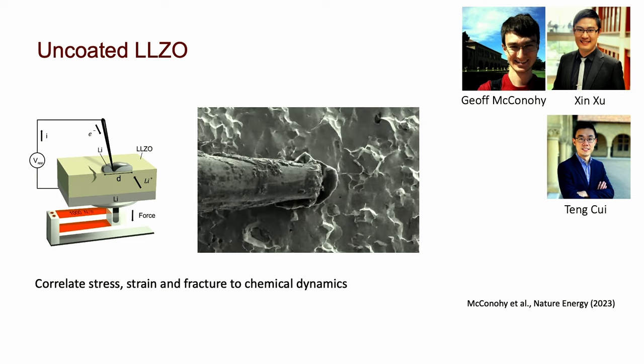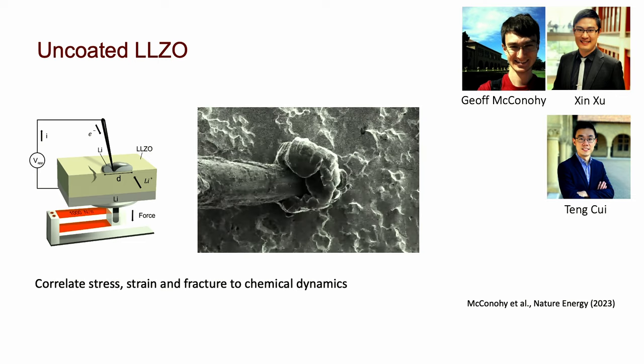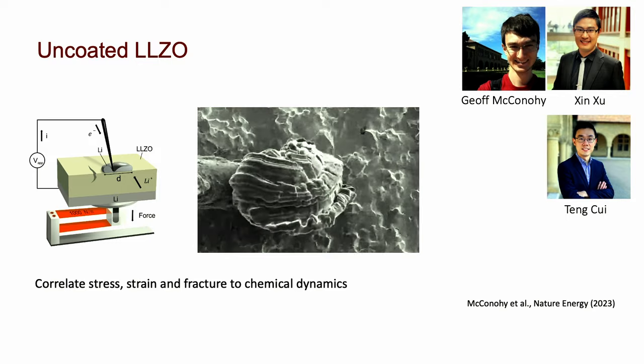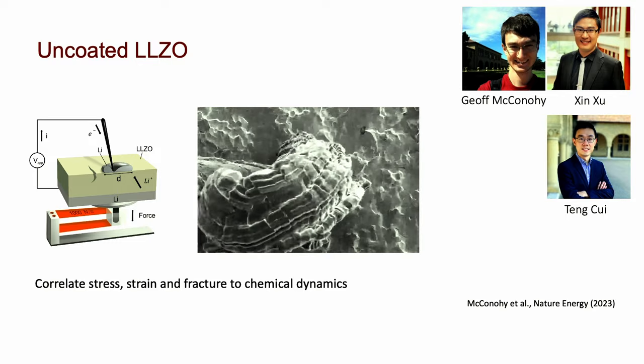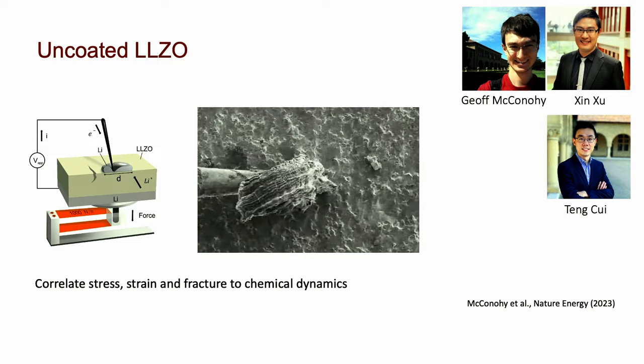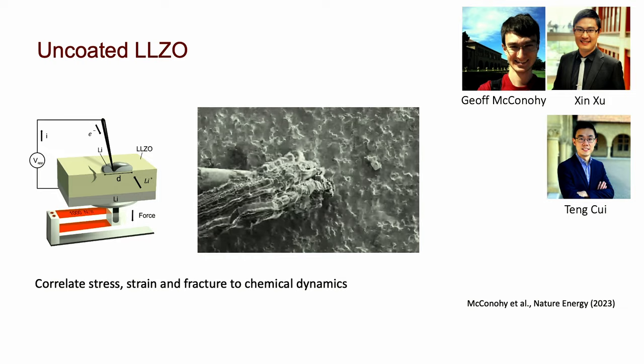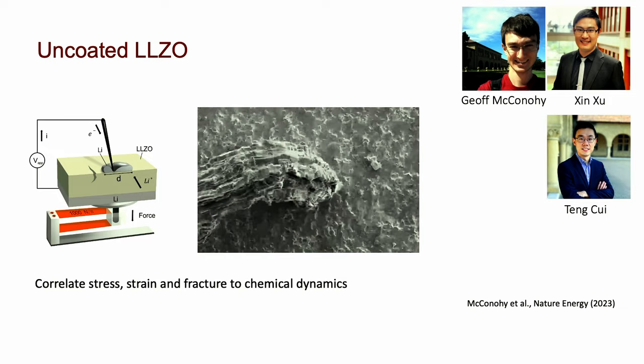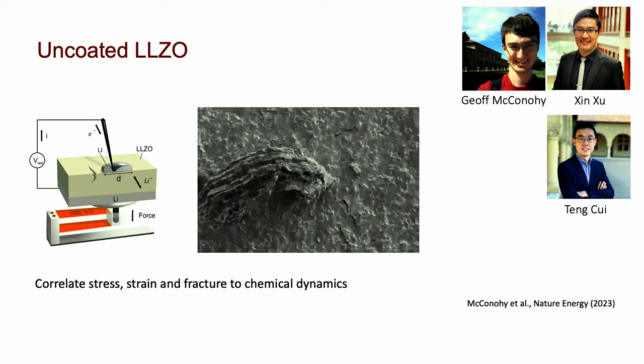When we do this experiment, we see lithium plating where the probe is attached, and it's going to be a little subtle. What we have is the formation of these lithium dendrites around this. So it finally happened here. With this, we can connect the formation of these features to the exact mechanical and electrochemical conditions.